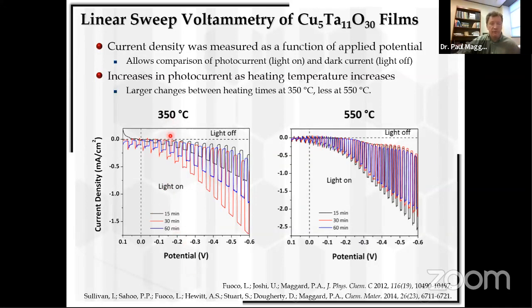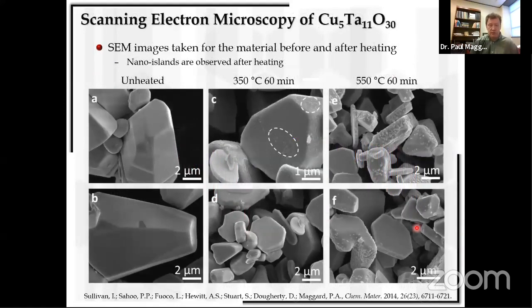The films at 350 showed a fairly high photocurrent, and as well, the films at 550 showed a high photocurrent. What I haven't shown you, though, is that if you don't heat these films at all in air, they have almost no photocurrent, which is strange for us. So we make the films, and it took heating them in air to see a significant photocurrent, to see the significant activity. And so we looked very closely at the surfaces to see what was going on. What's responsible for this behavior?